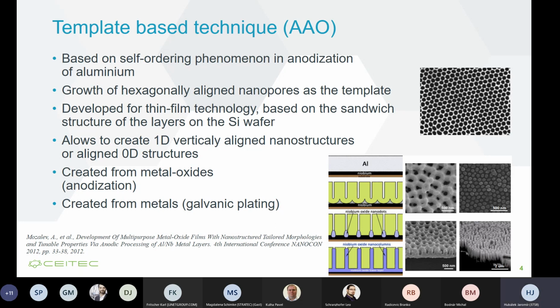This technique allows us to grow hexagonally aligned nanopores as a template, which you can see in the top picture, and this technique was developed for thin film technology. It is based on a sandwich structure in the left picture. It is a multilayer structure in the process, which allows us to create 1D vertically aligned nanostructures or aligned nanodots. So here are some examples of the template and the nanorods from the top view and side view.